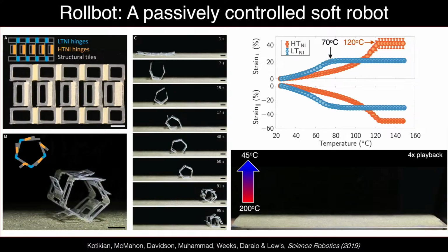But what you have here are these little rigid tiles, and you have the hinges that are made out of low and high TNI materials. And interestingly, the high TNI material is sitting here in the internal part, and the outer tiles are out of the low TNI material. And you're going to see why that's important in a minute. We want the low TNI material to always stay folded, and we want the hinges, which are the things that are propelling this, to fold and unfold.